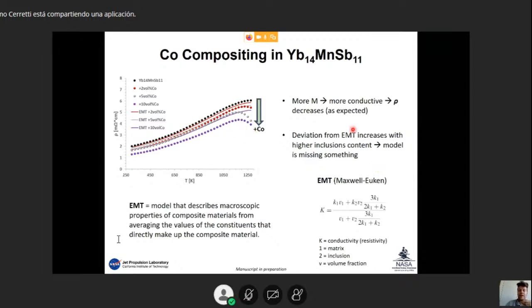The effective medium theory is a mathematical model which is used to predict the properties of a material, especially the electrical resistivity or electrical conductivity and the thermal conductivity. So I tried to use this equation to predict what the values of the electrical resistivity should have been, and the surprise was that actually it's more conductive than what this theory, which is largely used, would have predicted.